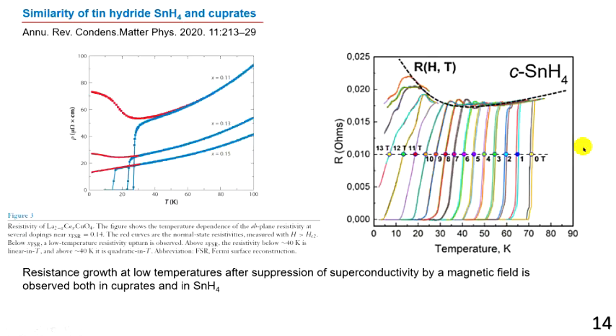On this slide, I would like to one more time underline similarity between the behavior of tin hydride and cuprates. On the left side, you can see temperature dependence of electrical resistance for cuprate. Red curve shows behavior of electrical resistance in high magnetic field when the superconducting transition is already suppressed. We see that electrical resistance grows at low temperatures. And absolutely similar behavior we see in the SnH4. The SnH4, when we suppress superconducting transition by high magnetic field, about 16 Tesla or more, we see the rise of electrical resistance at low temperatures.